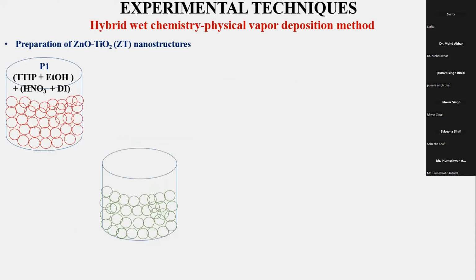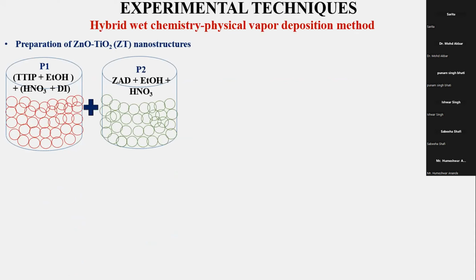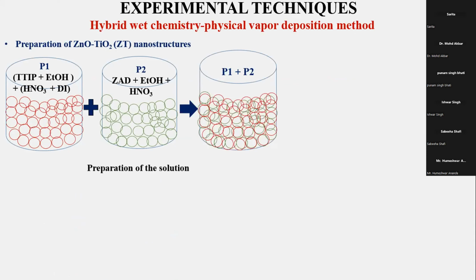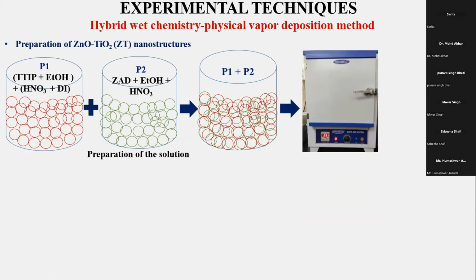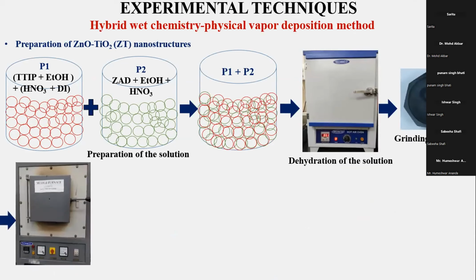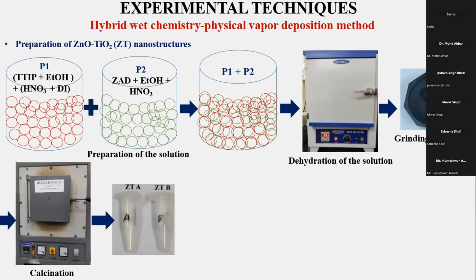Experimental techniques: the hybrid wet chemistry and physical vapor deposition method. We have developed zinc titanate structures through two precursors, in which one is titanium dioxide and in the second precursor it will be zinc oxide. When you do the wet chemistry route, you will get the zinc titanate, zinc oxide and titanium dioxide nanocomposite, which you dehydrate using a hot air oven, grind it, and with the calcination,